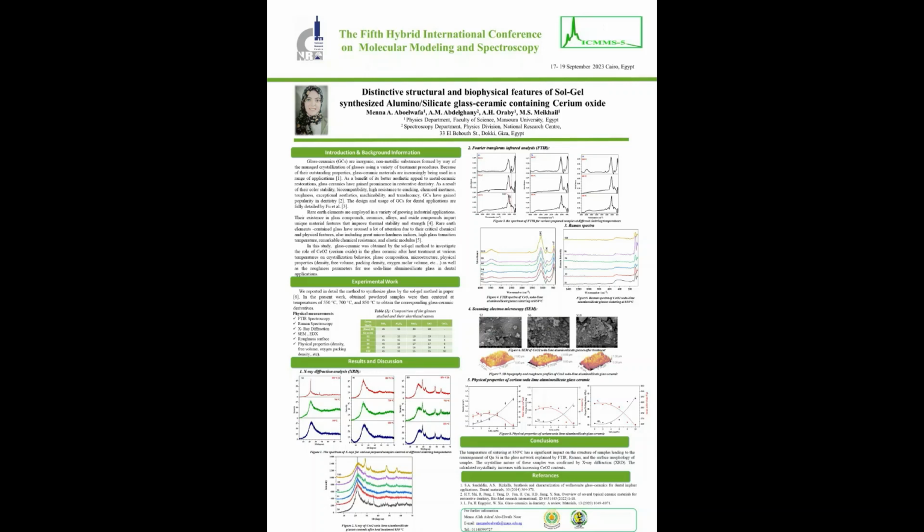In the results and discussion section, from XRD shown in figure 1, at the sintering temperature of 550 in sample S10, the crystal growth rate increased because it contained 10 mol% of CeO2. With raising the temperature to 700, peak lines appear in samples with a greater mole percent of cerium oxide than at the 550 temperature. This tendency is accelerated by further temperature increases up to 850. The number of nuclei, crystal growth rate, and nucleation rate all rose significantly after 850. Figure 2 shows the X-ray of CeO2 soda lime aluminosilicate glasses after sintering temperature 850.